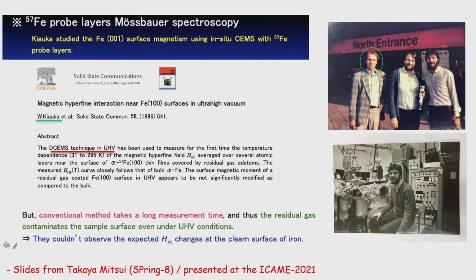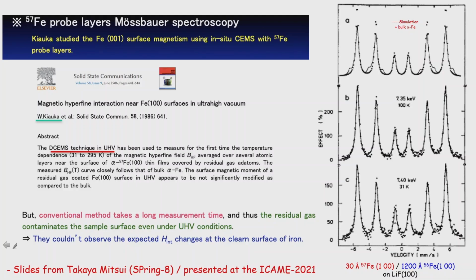and in fact, Kiauka was sharing with me this same system, the ultra-high vacuum system for depth-selective Mossbauer spectroscopy in Duisburg. We were both sharing this system at that time. He was trying to see this effect, and I was trying to see what happens with FCC iron expanded. You see that this is the spectrum that Kiauka took at that time, with a measurement of 30 angstroms of iron-57, and this is the simulation. If there were oscillation, he should see these shoulders in the spectrum, and he didn't see them.